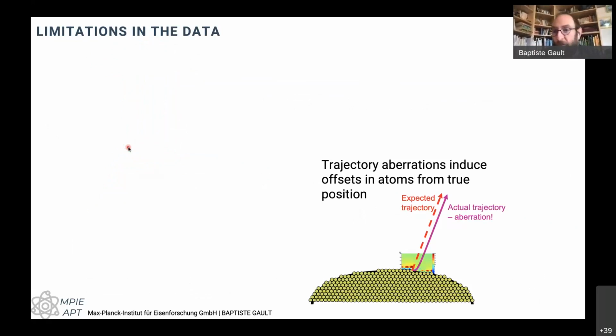There's also the physics that's playing some tricks and limiting what we can do. So first, if we look at the distribution of the electric field at the apex, what we have is actually something that is rough. I'll get back to this in the next few slides, but basically the surface is not smooth, right? Down at the atomic level, we are trying to make something spherical out of an assembly of atoms that's typically on a square lattice or a cubic lattice. So we always end up with a series of terraces. And these terraces actually cause the field to be not homogeneously distributed, and there will be slightly higher field at the edge of the terraces because these atoms have basically fewer neighbors to share their electrons with, so they are a bit more exposed to the field.